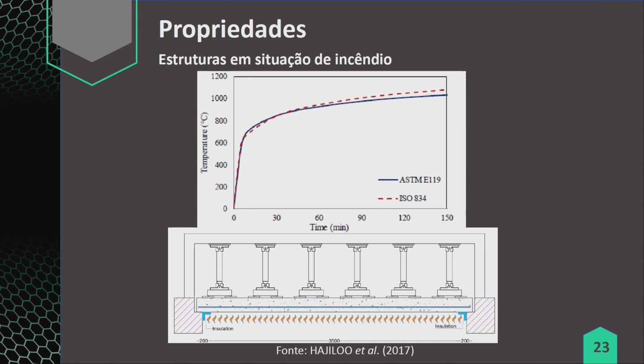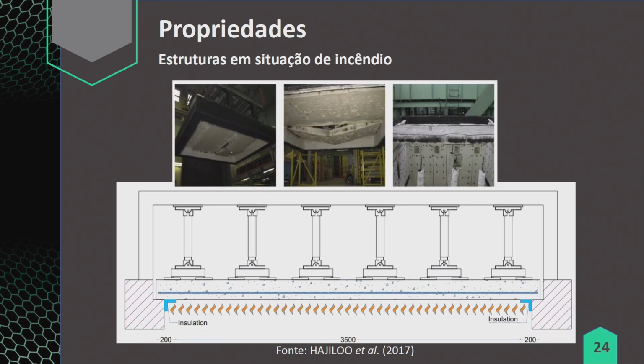This is the curve for fires in residential areas. Normally in an apartment or a house, a fire will reach 700 Celsius due to the materials and fuels that we have. We may have wood, we may have gas and electrical appliances. And this standard, this curve, has a safety coefficient, and the temperature is a little bit above 1,000 Celsius. Here you can see the structure after the test, showing when the stability was lost.